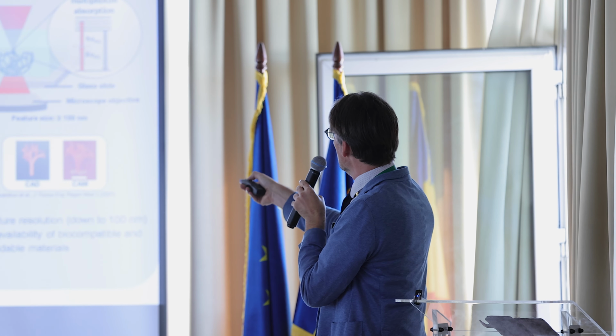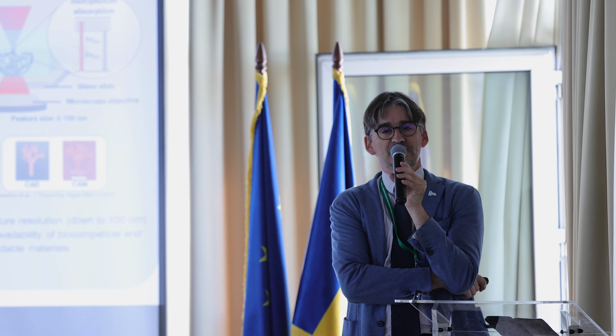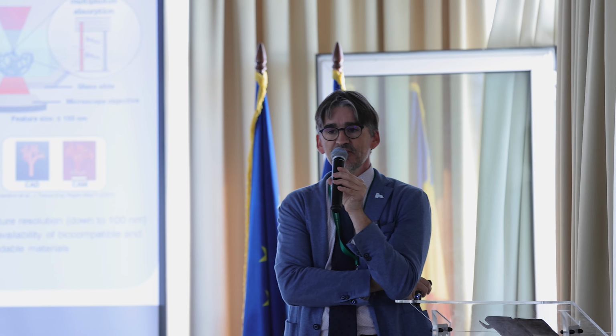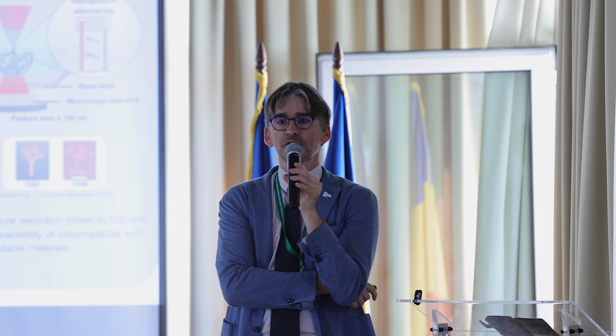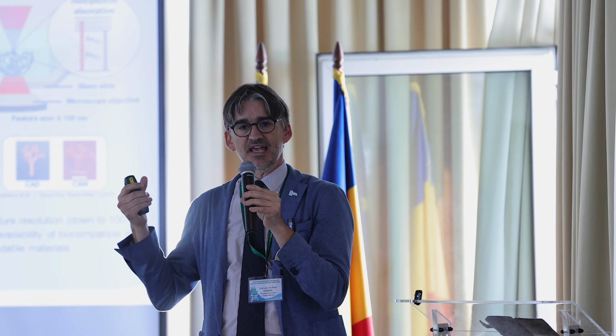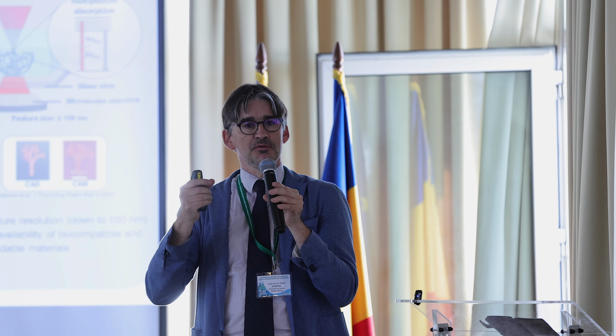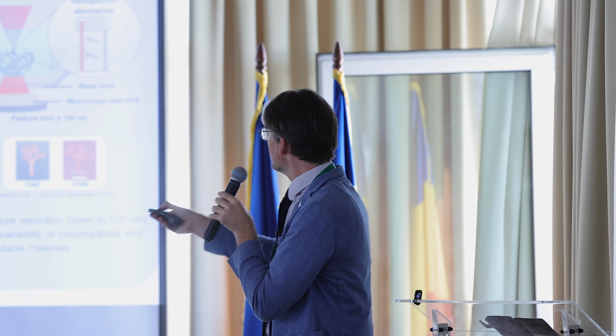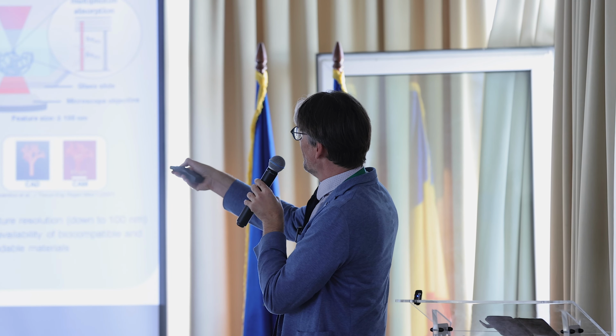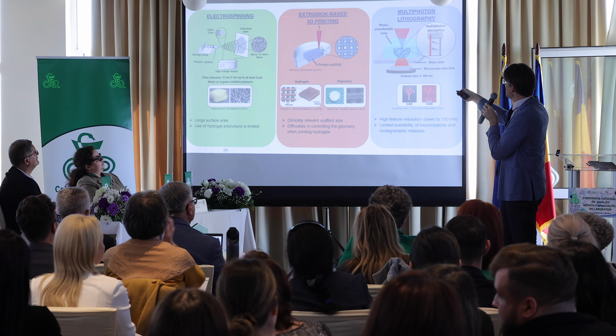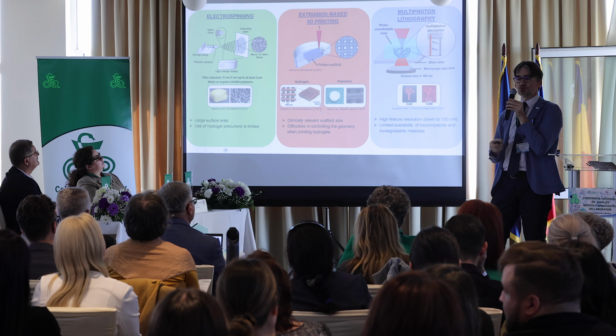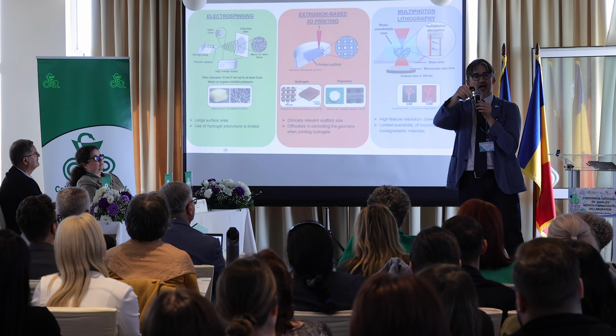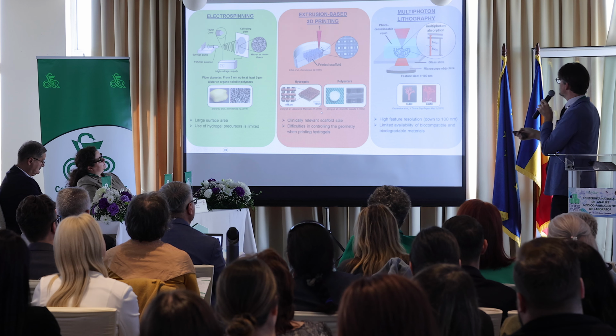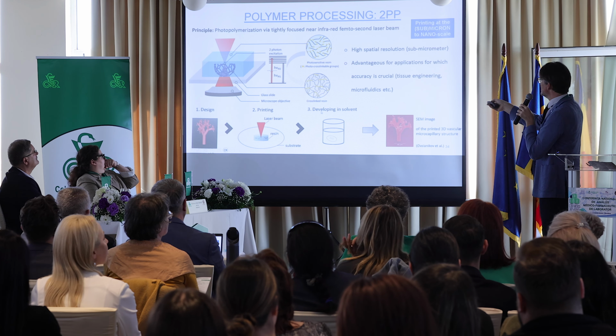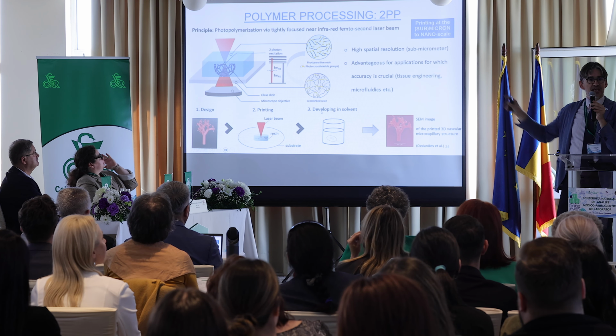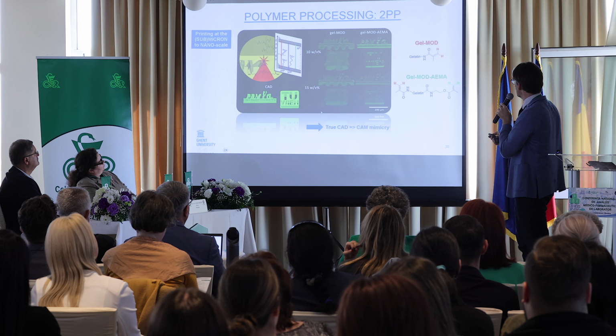What this two-photon processing enables you is actually to develop polymer features that have sizes which are lower than 1 micrometer. So that means that this technique as such will most likely never be used for developing entire scaffolds, but you can use this technique to functionalize scaffolds obtained through electrospinning or scaffolds obtained through extrusion printing. So you can use 2PP to write additional patterns on the first two techniques mentioned. Principles shown here, I will not highlight that. If there's an interest, I'm happy to further discuss that.